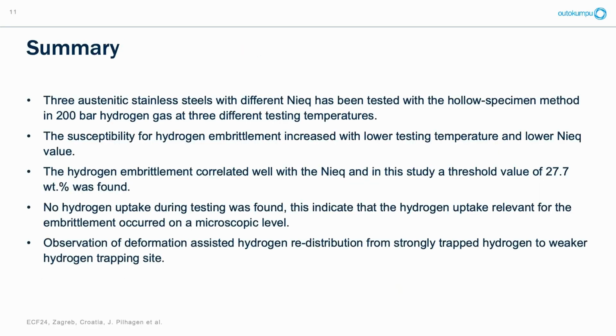So to summarize, 3 austenitic stainless steels with different nickel equivalents have been tested with this hollow specimen method in 200 bar hydrogen gas at 3 different testing temperatures. The susceptibility to hydrogen embrittlement increased with lower testing temperature and lower nickel equivalent values. The hydrogen embrittlement correlates well with the nickel equivalent for these grades, and we found a threshold value of 27.7. We observed no macroscopic hydrogen uptake, which indicates that the hydrogen uptake relevant for the embrittlement occurred on a microscopic level. And we also observed deformation-assisted hydrogen redistribution from strongly trapped hydrogen to weaker hydrogen trapping sites when deformed.